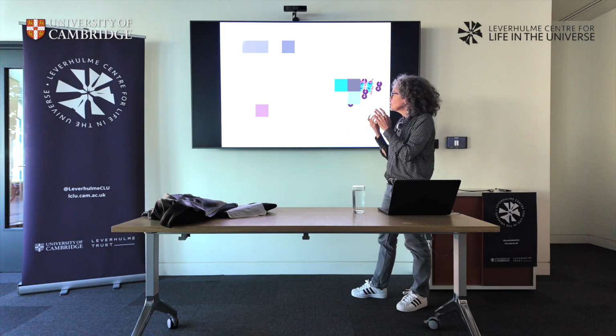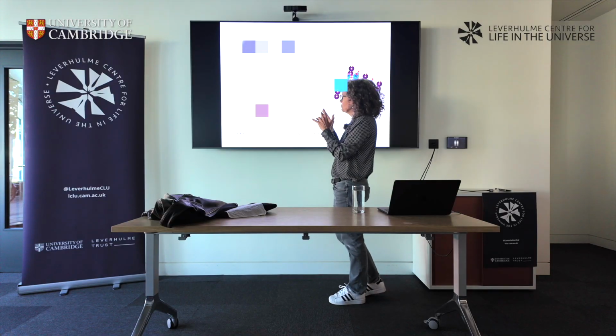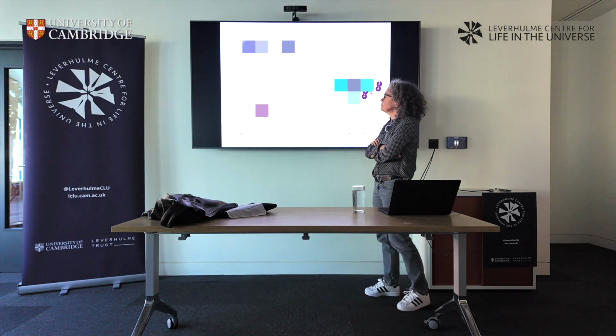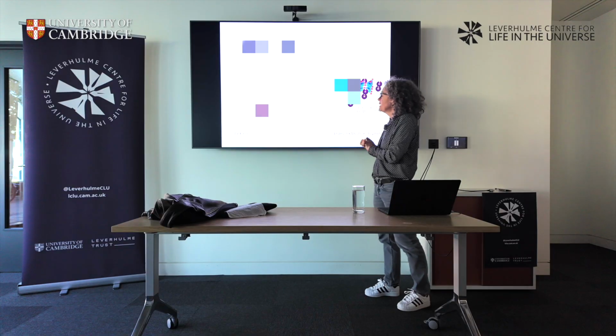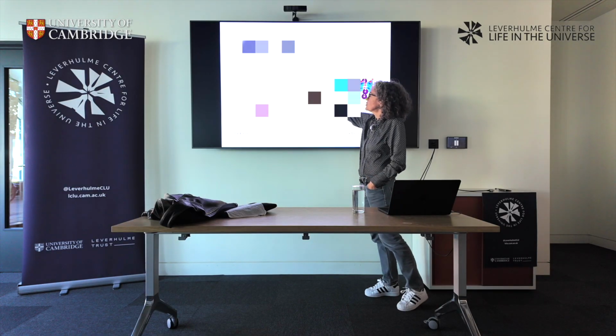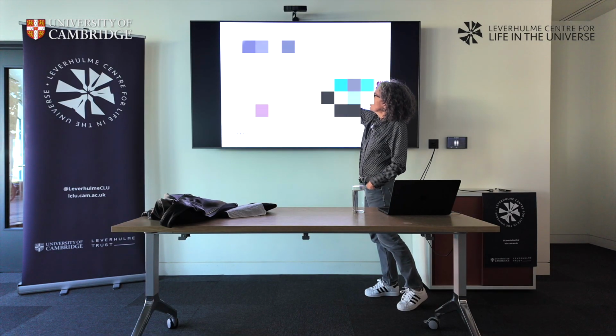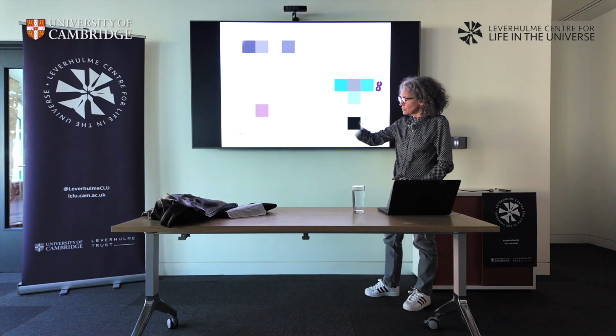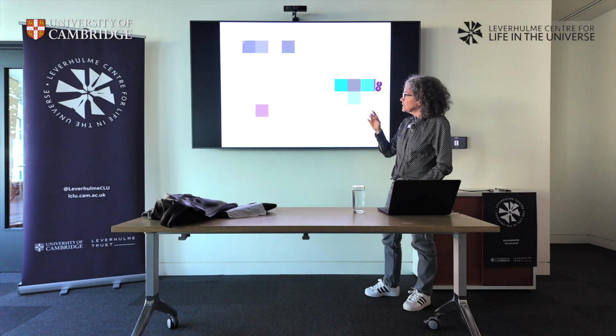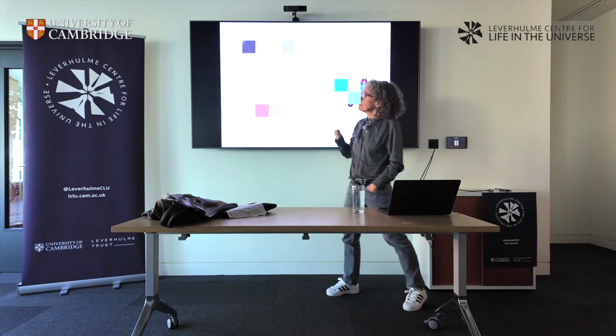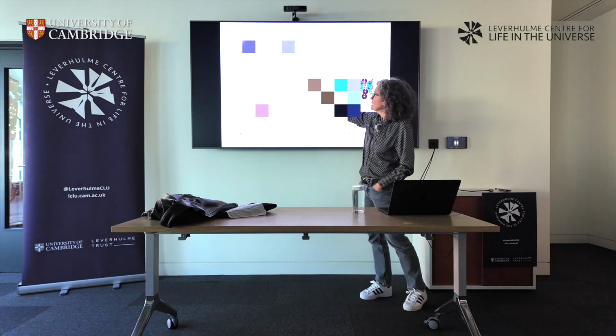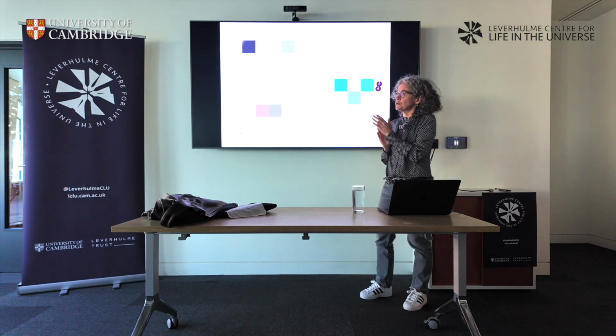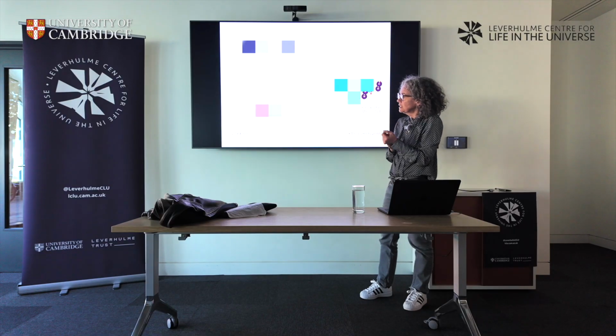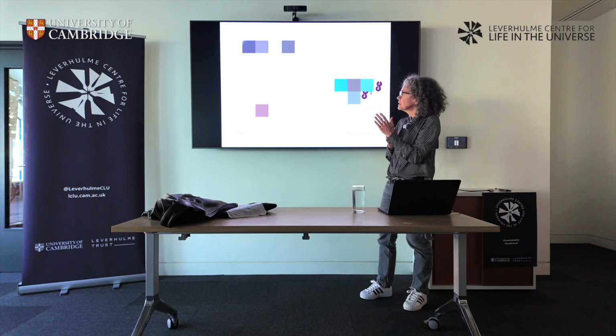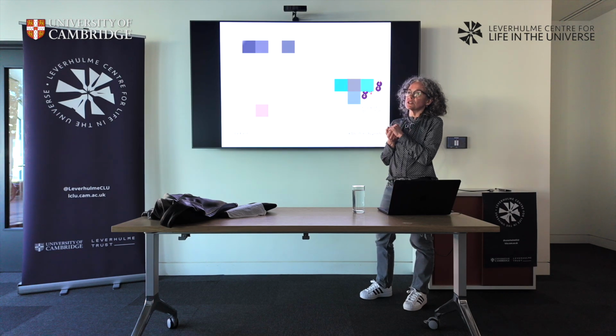Okay, so I won't go into the details, but we tried to fit this data with just one shell of atoms, and the best fit we got was for xenon-oxygen, in which case you get 3.2 angstrom. What I haven't shown here is that the xenon edge is shifted in this compound compared to xenon gas. During the experiments, we had xenon gas as a standard, and there was a shift of the energy, which tells you that there is a redox change.